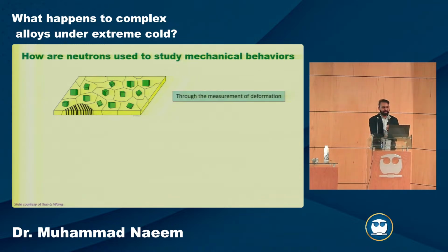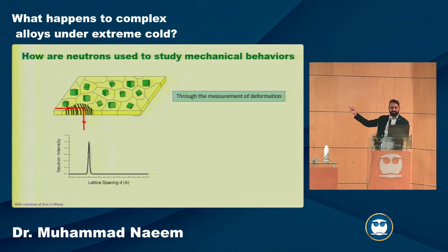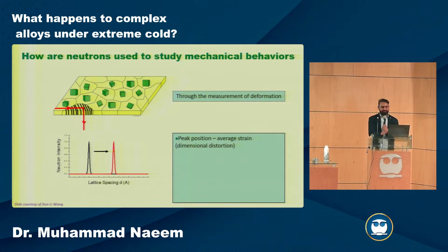orientations. And then you have this radiation which comes, it interacts with your material, and you get a diffraction peak, which has a position, some intensity, some broadening. So all the information will be obtained through these peaks. Okay, then if we apply a force on it, what will happen? This peak can move, right? Depending on if it's tension or compression.